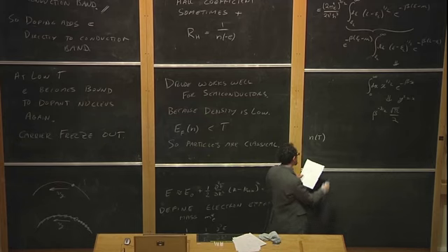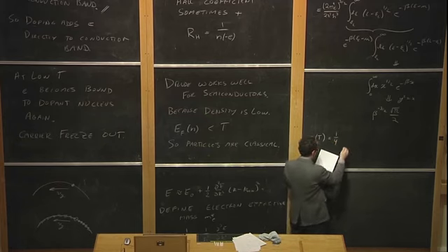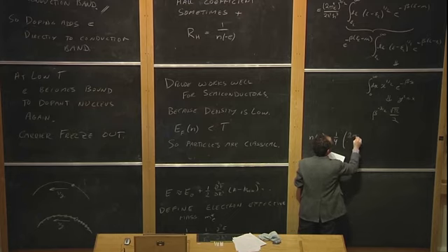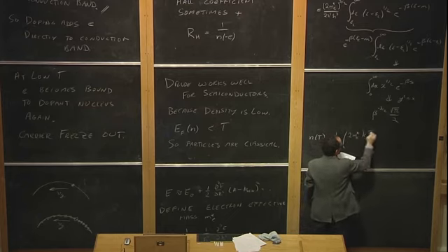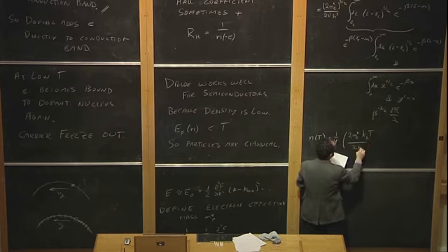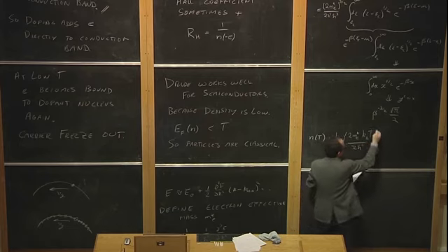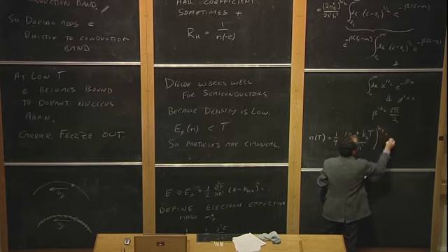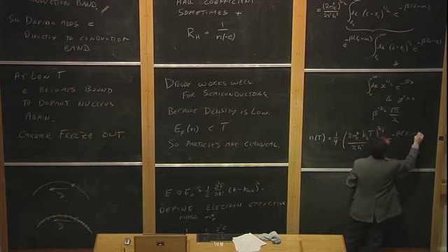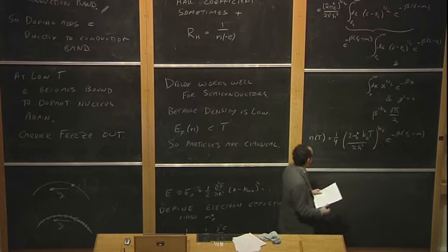Okay? So we put that all together, and we end up getting the density of electrons in the conduction band as a function of T, putting together all those factors: 1/4 times (2 m star of the electron k_B T over pi h bar squared) to the 3/2 times e to the minus beta (energy of the conduction band minus mu). So this is our expression.